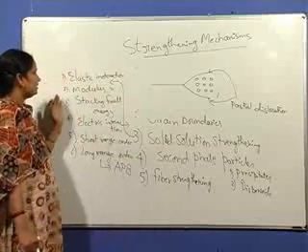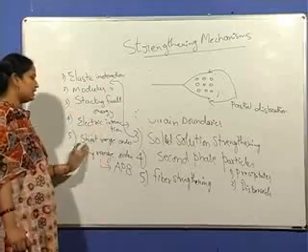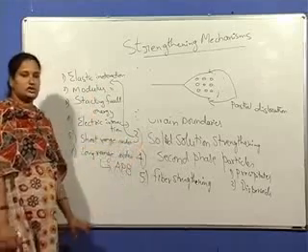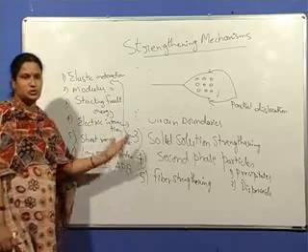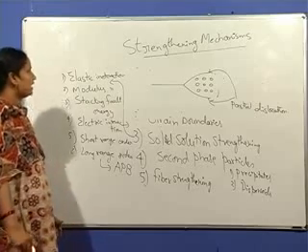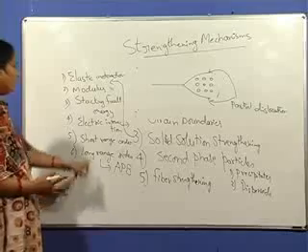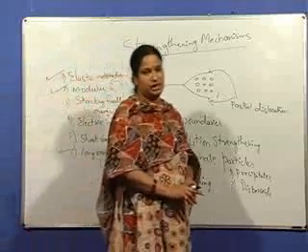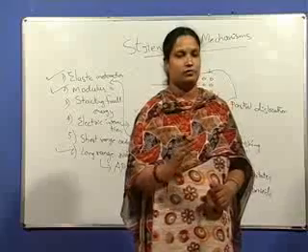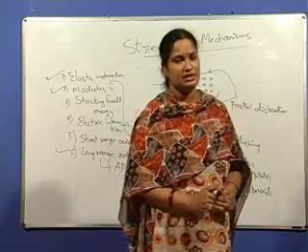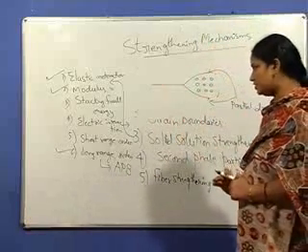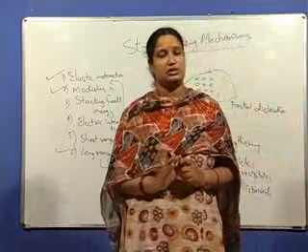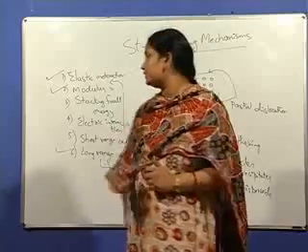Whereas all these, elastic interaction, modulus interaction, stacking fault energy, electric interaction, short range order, were discussed, and all these are the mechanisms of solid solution strengthening. Either one of these contributes to solid solution strengthening. Among these, elastic interaction, modulus interaction, and long range order are temperature insensitive. That means they occur for long ranges. Whereas stacking fault energy, electric interaction, and short range order are of short range. That means these three are temperature sensitive.